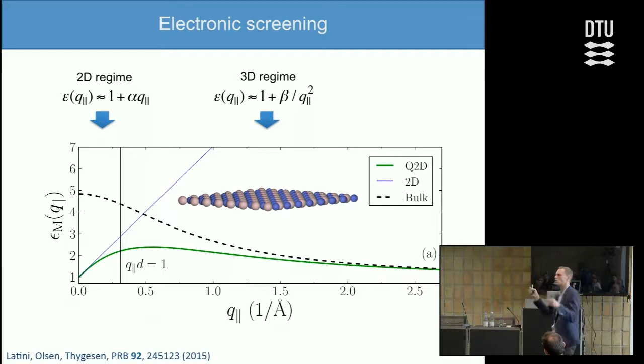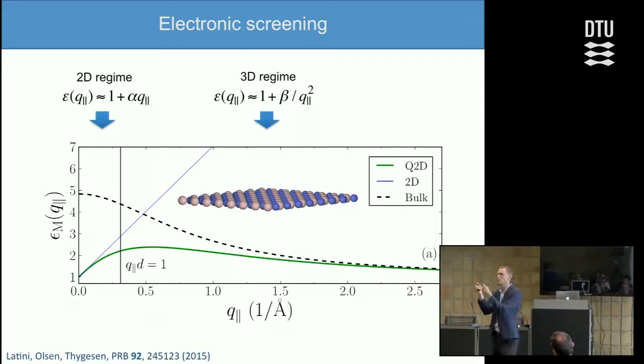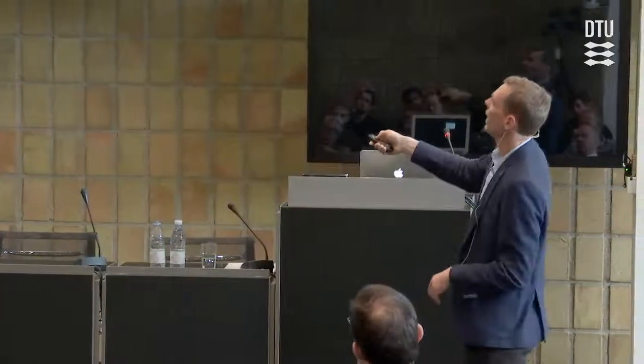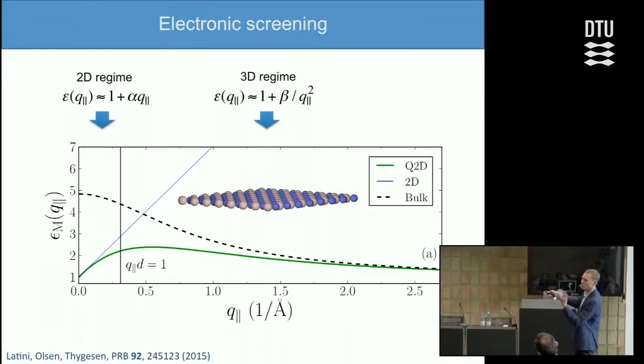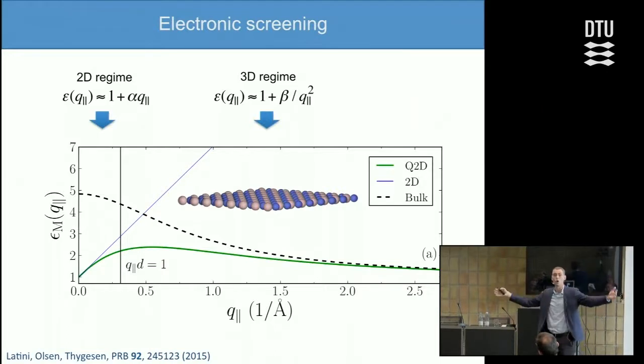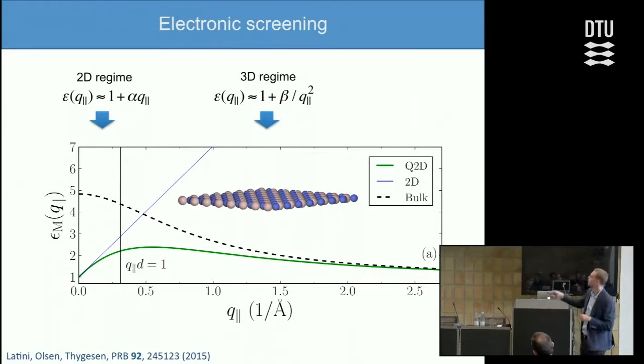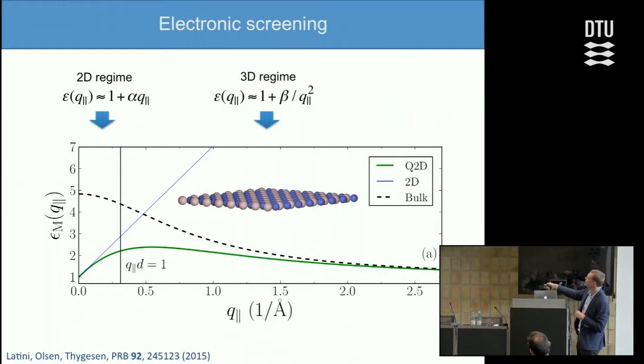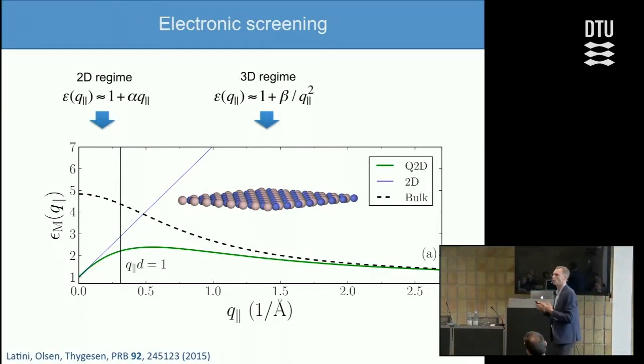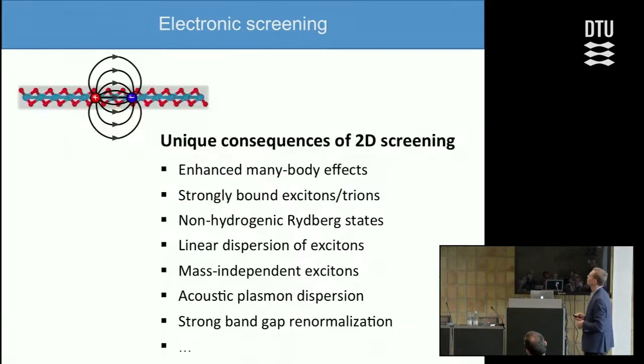This corresponds roughly to the situation in real space where the particles are close to each other. But when the particles are far away, that means we have wave vectors in reciprocal space that have wavelength longer than the thickness of the material, then there is a clear deviation and the dielectric function becomes linear in Q rather than constant, as we know from 3-dimensional systems. So this is the mathematical consequence of these peculiar screening effects in 2 dimensions.